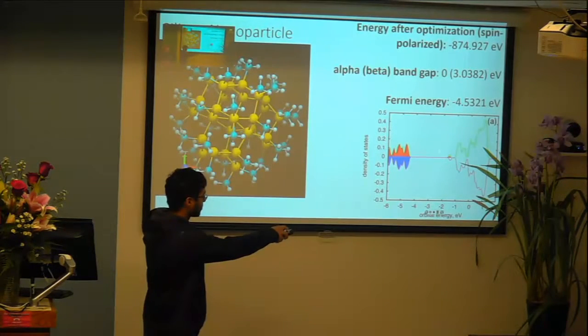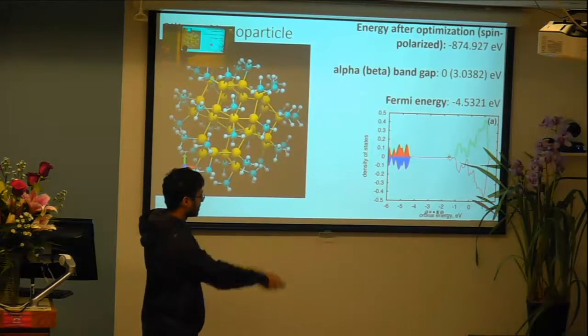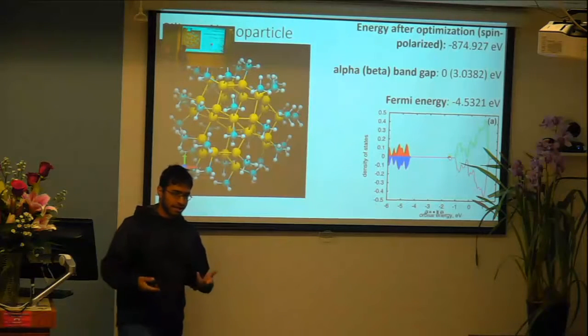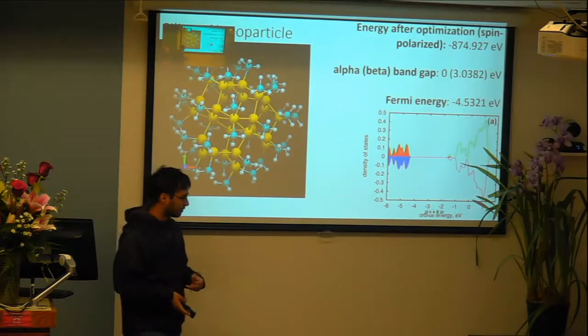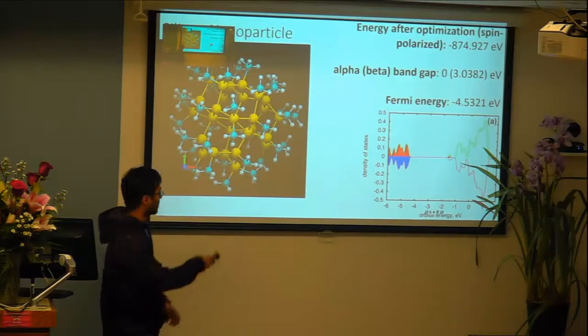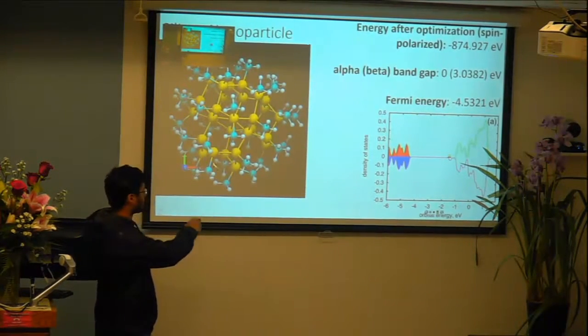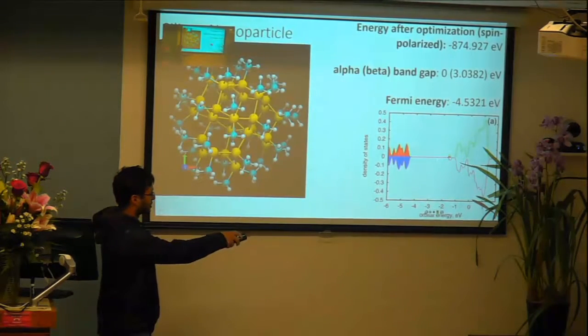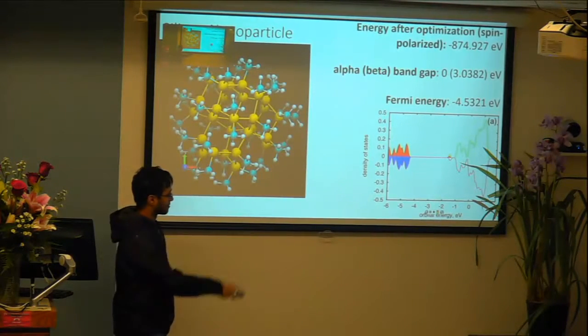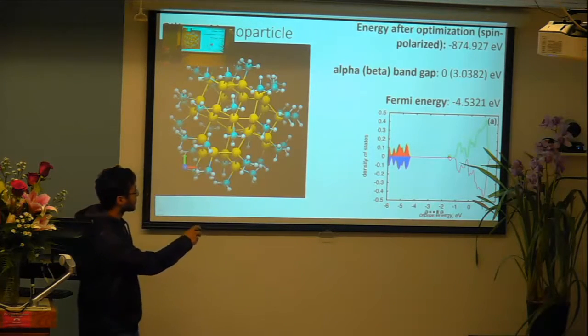So we can see that there are some electrons in the conduction band here, and this is likely because the model was not oxidized. So further work could be done in order to actually oxidize the lone silicon nanoparticle and remove electrons from the conduction band. And we'll see a consequence of not oxidizing this model in a couple of slides.